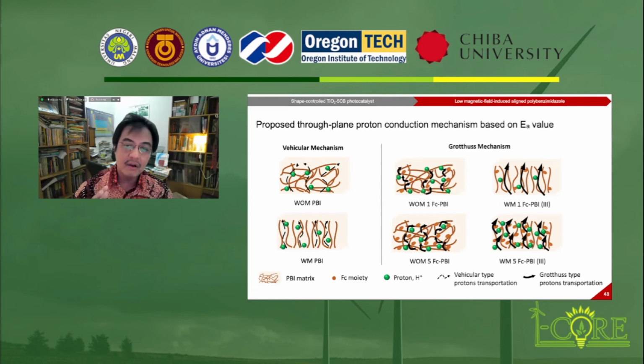After the orientation of the polymer changes toward the magnetic field's direction, the activation energy decreases, and this shows that aligned proton exchange could enhance the proton conductivity of the membrane with the increase of the temperature. It is also suggested that after the addition of the ferrocene, the dominant proton conductive mechanism is the Grotthuss mechanism.